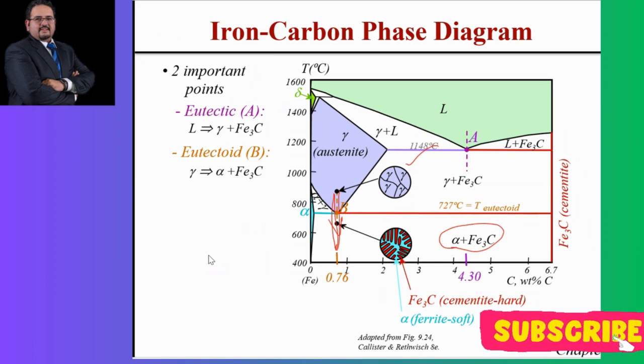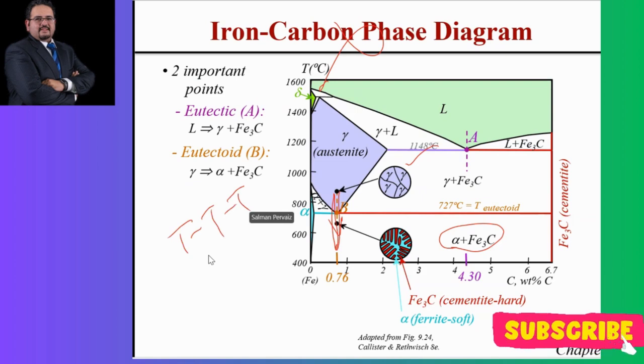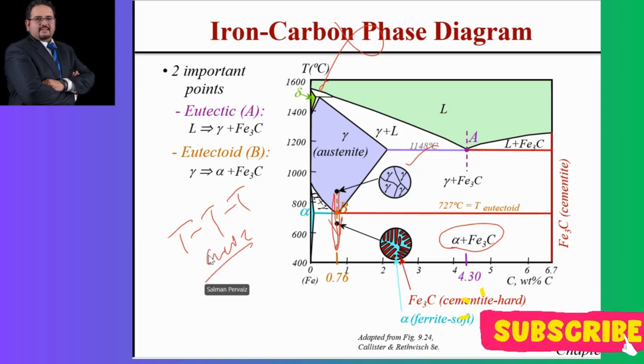But you didn't know that there are more possibilities with respect to time. You don't see this in the phase diagram. So you need to go to the time-temperature-transformation curve to see the time-dependent possibilities. You see that the reaction can go into pearlite, depending on the delta T, how quickly you cool it. It can go to martensite or it can go to the bainite structure.